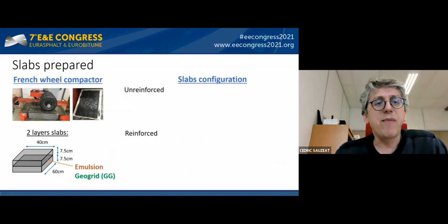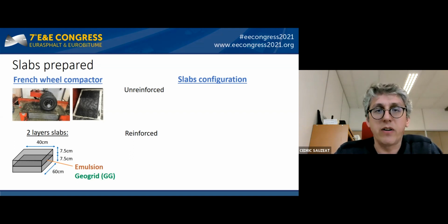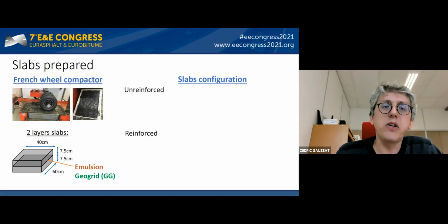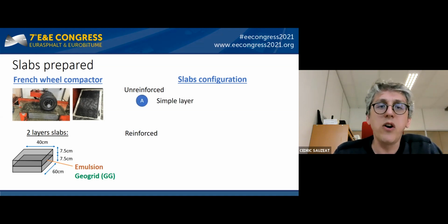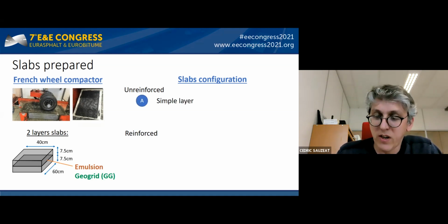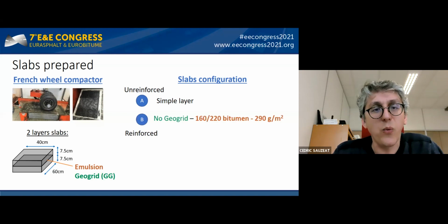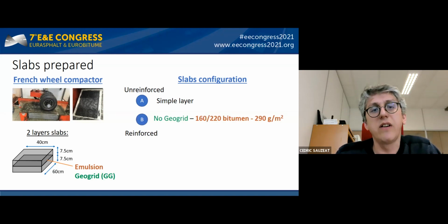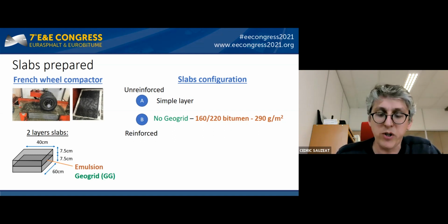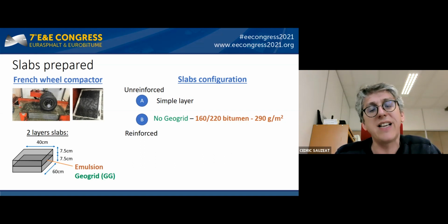We prepare a slab with these materials using a French wheel compactor. We had five slab configurations. The first configuration is an unreinforced slab made with only a single layer. The second slab is made with two layers, but contains no geogrid. At the interface, we have a pure bitumen emulsion. We have used a pure bitumen emulsion as tack coat.